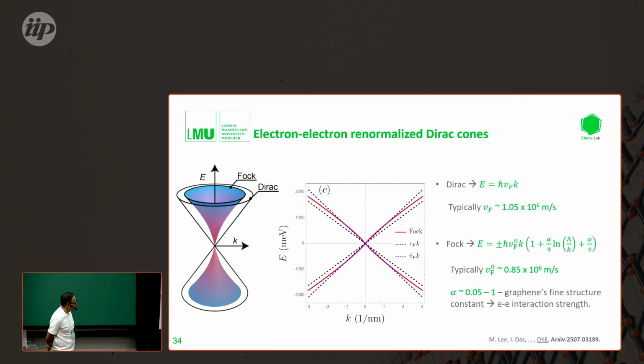So our best explanation is electron renormalization, and I think this was first introduced by Paco, right? Who is here in the audience. The idea is that if you tune the Fermi energy in graphene very close to the charge neutrality point, then the density of the electrons becomes so low that the electrons stop feeling one another. They basically stop screening one another, and therefore the Fermi velocity at the charge neutrality point can be somewhat enhanced. And if you start filling electrons back into the system, at one point screening takes over again, the electrons screen each other quite well, and then the Fermi velocity just reduces.